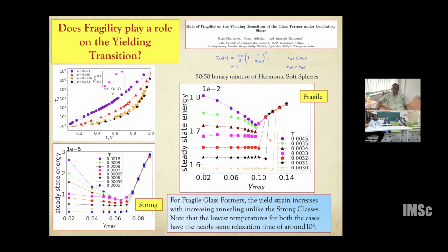So this physics was somewhat surprising, at least for us. Strong and fragile concepts are typically useful when you're dealing with liquids, not when you're dealing with amorphous solids. There you are talking about brittle or ductile behavior, which we feel is related to your annealing protocol. But the changes in the oscillatory phase diagram for a strong and a fragile glass forming liquid, when you generate glasses from them, this difference was surprising.